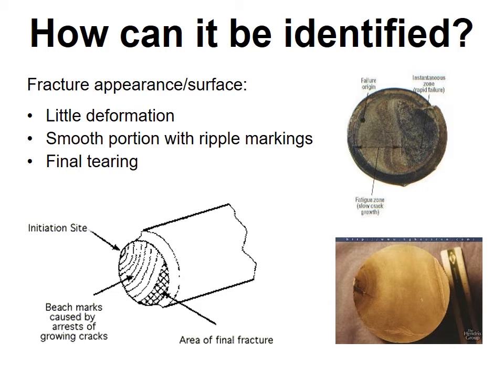Although fatigue fracture is brittle in nature and does reveal areas of brittle fracture under fractography examination, the fracture surface has a unique appearance that is different from that of brittle failure. It consists of two areas where one portion is smooth and shows beach mark striations spreading out from some discrete points indicating where the fracture was initiated. These striations are often a feature of service failures associated with non-uniform conditions and intervals of rest. The remaining surface, which indicates the final tearing, will display either a crystalline or fibrous appearance and therefore can be a brittle or ductile fracture or even a combination of both, and this occurs when the area can no longer sustain the load.